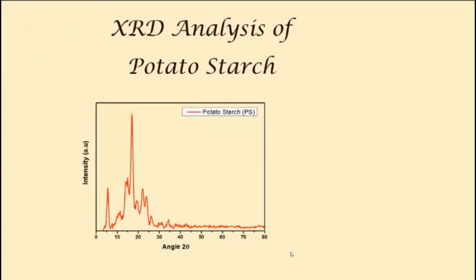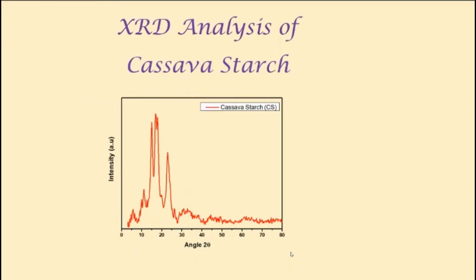This is the XRD analysis of potato starch, having a high intensity sharp peak at 16.9, and several other peaks are also seen. Next is the XRD analysis of cassava starch, having a broad and high intensity peak at almost 18, 2 theta equal to 18.